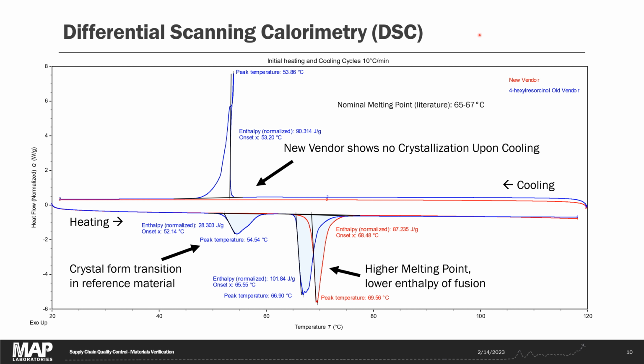So we ran our DSC on our old vendor and our new vendor. We ramped at about 10 degrees Celsius per minute for the heating and cooling. And the first thing you have to look at when you're looking at a DSC plot is what direction is positive and what direction is negative. And here we have exo up. That means exotherms are positive here and endotherms are negative. Sometimes this will say endo up or endo down. So in this case, we have endotherms going negative. These are melting events, and exotherms going positive.